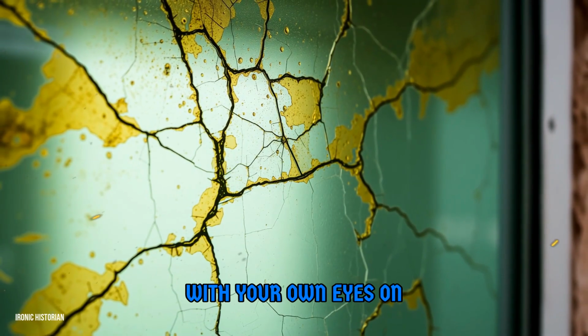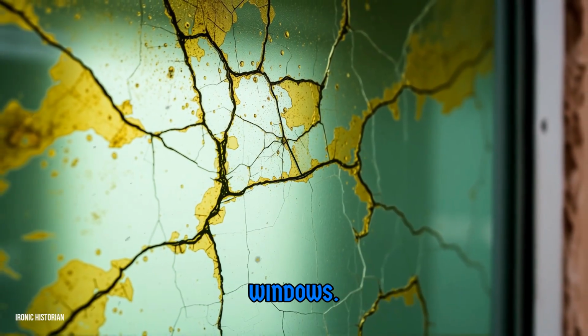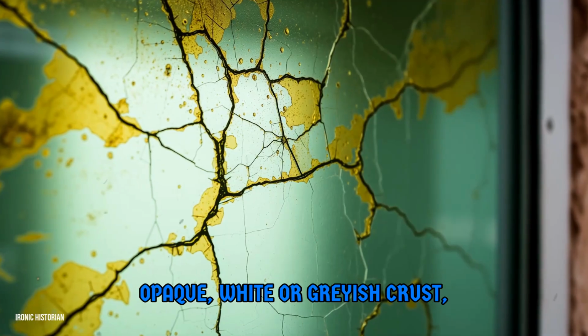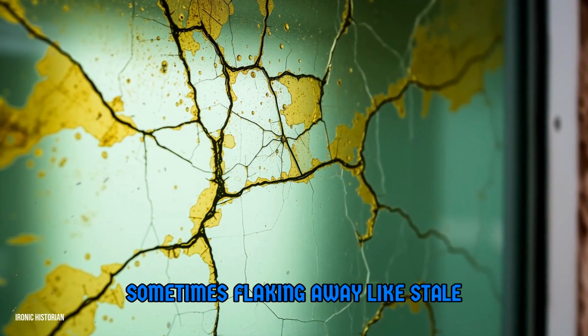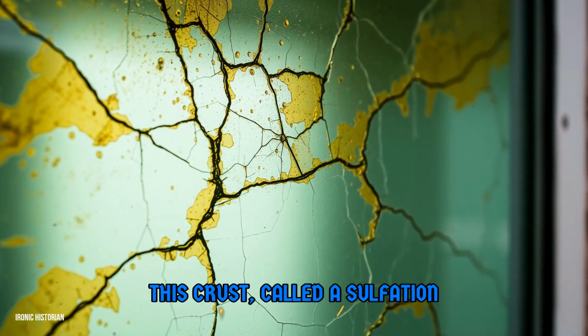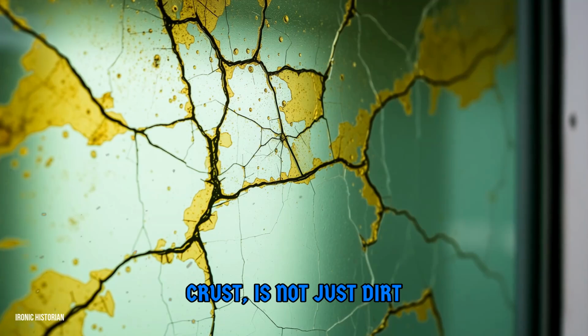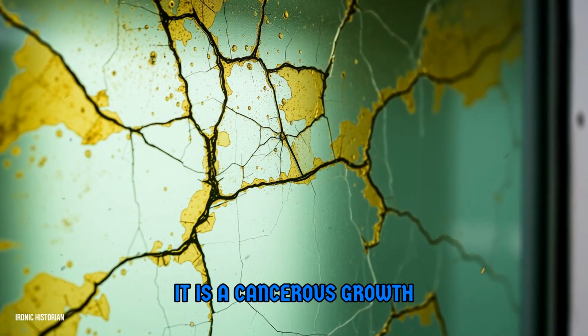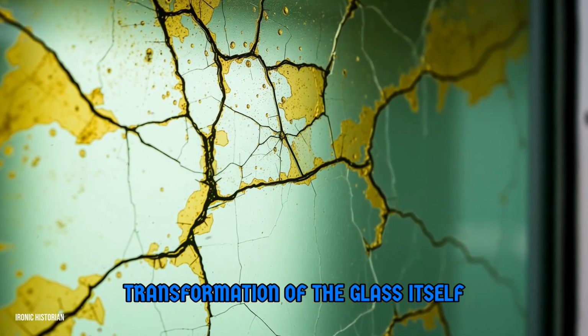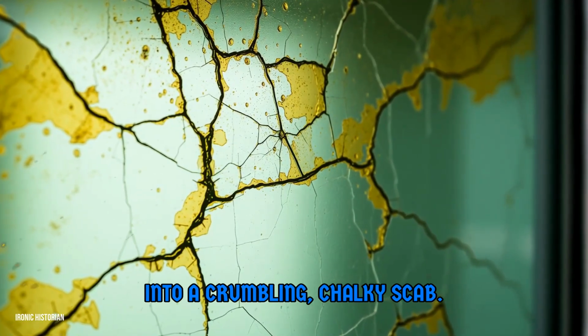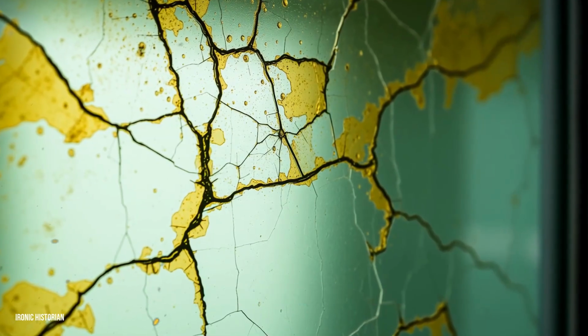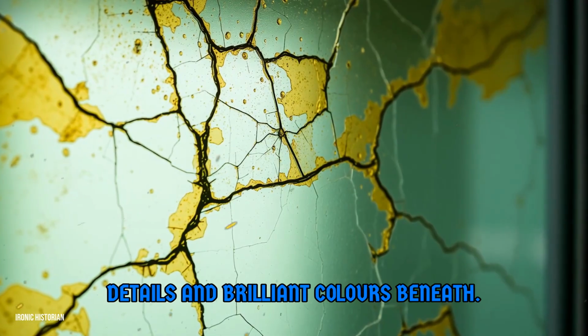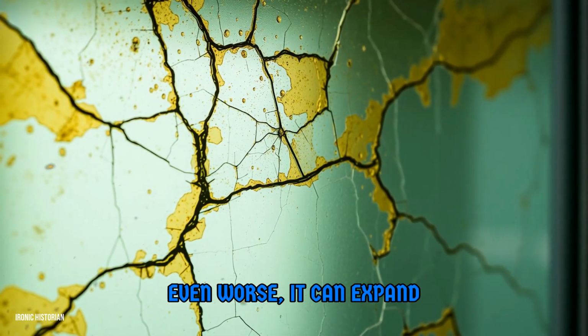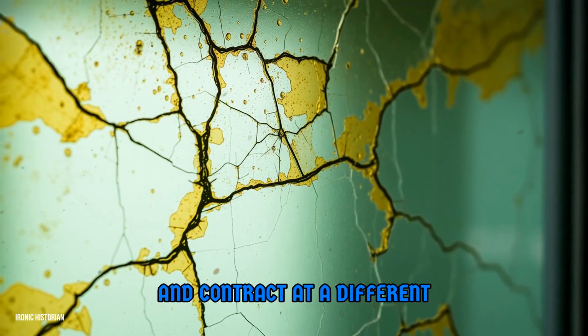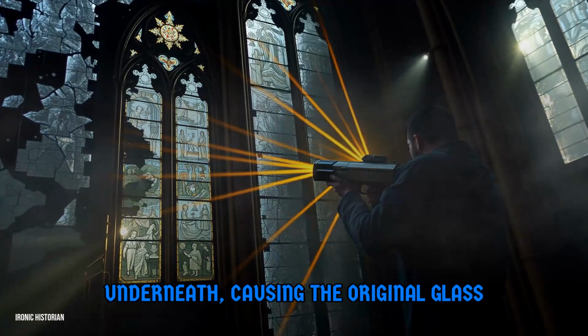You can see this damage with your own eyes on the outside of neglected medieval windows. It looks like a rough, opaque, white or grayish crust, sometimes flaking away like stale pastry. This crust, called a sulfation crust, is not just dirt sitting on the surface. It is a cancerous growth from the surface, a permanent transformation of the glass itself into a crumbling, chalky scab. As this crust grows thicker, it completely obscures the painted details and brilliant colors beneath. Even worse, it can expand and contract at a different rate than the healthy glass underneath, causing the original glass pane to crack and splinter from the stress.